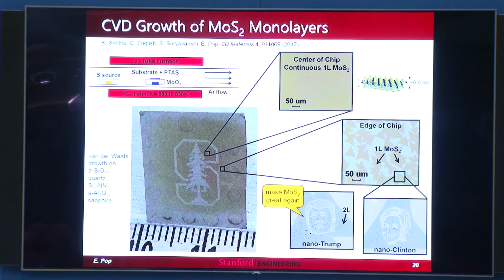On a more serious note, you will notice that the nanoscale presidents look like they have acne or chickenpox, right? Their faces are dotted. And so that's actually bilayer MoS2. Our growths are not perfect. Sometimes we get these beautiful monolayer coverage, but sometimes we get a few bilayer regions, right? And when I first saw this, I got really worried. I said, that's a 100% variation in layer thickness. You go from 3 atoms to 6 atoms. That's probably bad for any kind of large-scale integration. We really ought to study that.